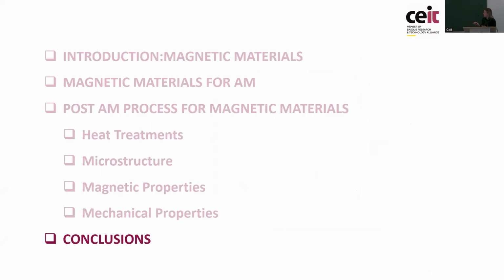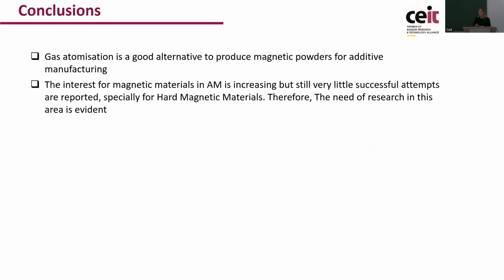So, as conclusion, as Jose Manuel said, the gas atomization process is a good alternative to manufacture soft magnetic and hard magnetic materials for additive manufacturing, because we have this feasibility of tuning the powders for the application. And also, it's important to know that there is a high interest in magnetic materials for AM, but still in the literature, there are not a lot of successful attempts. So there is a need of researching these materials in AM.